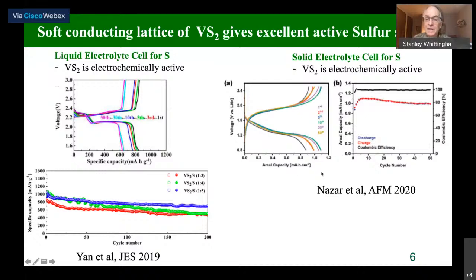And on the right-hand side, I show you again some data of Linda Nazar's. This is now in an all solid state cell. And you can see again, she's got 50 cycles out of this with good Coulombic efficiency and good capacity. So these metallic materials are both useful as active materials and as supports. And in this particular application for sulfur, the vanadium disulfide is also electrochemically active.